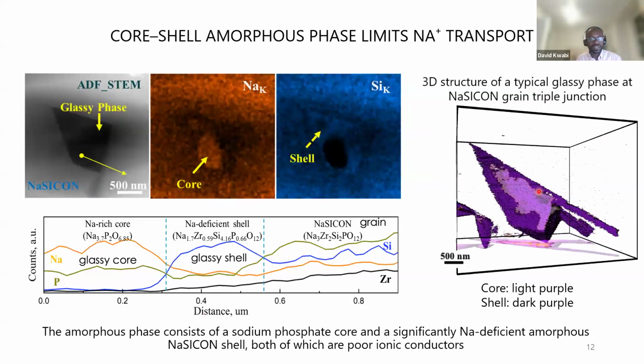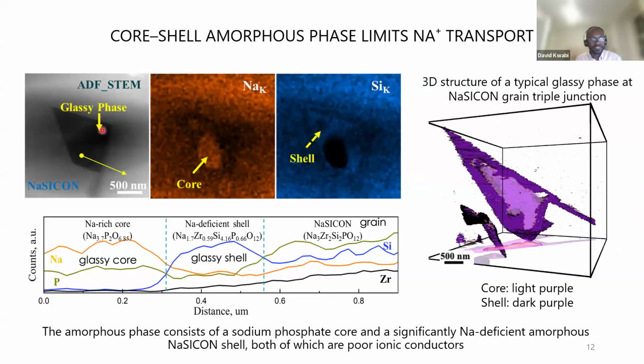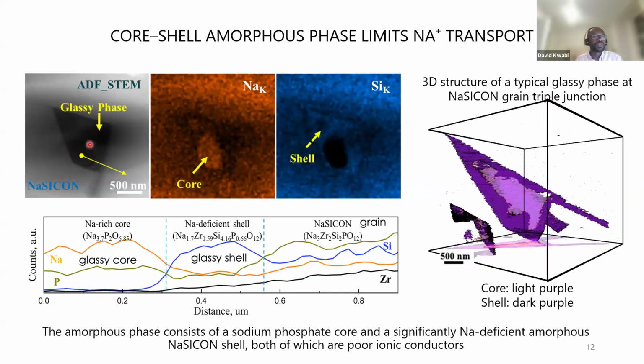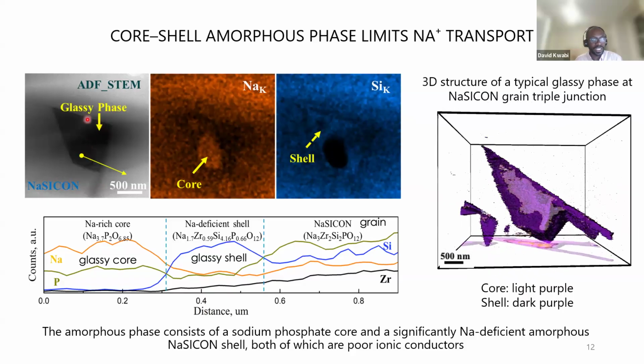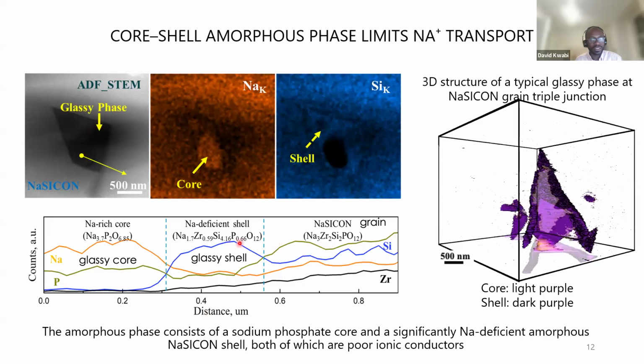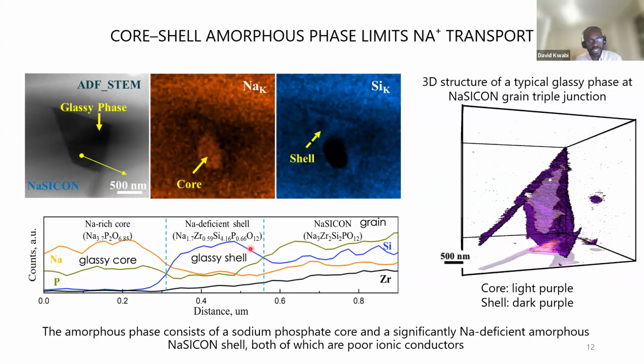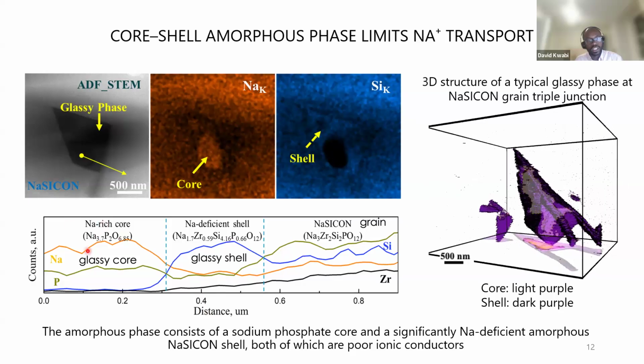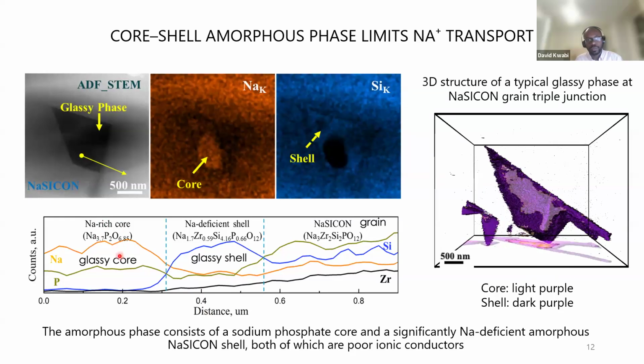So the next thing we discovered is that the glassy phase is actually a very different chemical composition than the crystalline phase. It contains a shell that is a sodium deficient version of NaSICON, and then it has a core, which looks very much like sodium phosphate. And you can see how this core-shell microstructure is arranged on the right plot here. Both of these materials are poor ion conductors, and so we want to avoid forming them because they would lead to degradation in performance of our membrane.